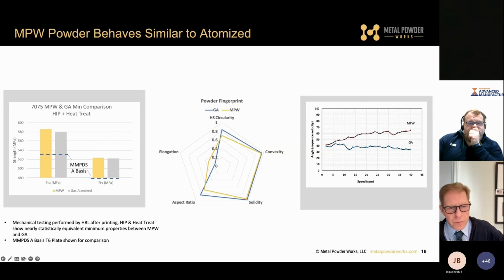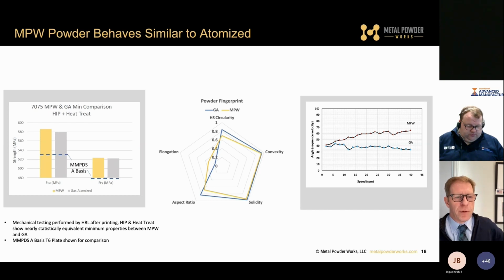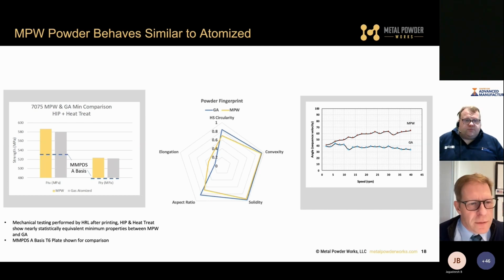We've done some comparisons with Purdue University on different things. On our first chart, we looked at printing a 7000 series aluminum. So we started off with 7075. We added the HRL process to both materials. Gold is the Metal Powder Works powder. Gray is the gas atomized powder, and effectively, you get the same properties back out. I could say that Metal Powder Works is slightly higher, but we're talking single-digit megapascals.